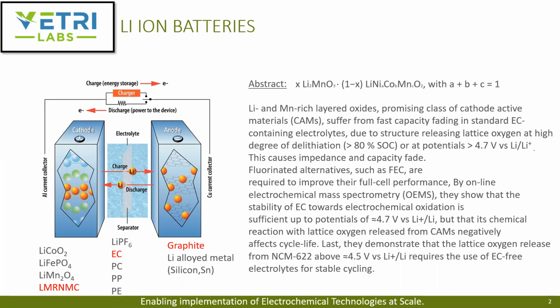They have further looked at separating the mechanism using electrochemical mass spectrometry. They show that electrolyte stability is not the root cause, whereas the interaction between the electrode and the electrolyte is the primary root cause.